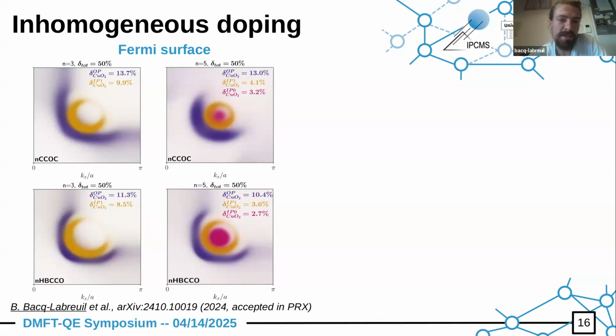Yes, I mean, what you see here is basically the pseudo gap in principle, right? That you have arcs forming. Of course there is always a grain of salt here because there is periodization involved, but in principle this is a pseudo gap, and we see it also in the momentum-resolved spectral function. So in principle we could also discuss the pseudo gap from these calculations. Here it was not the goal, so we did not do a very fine-tuning of the doping.